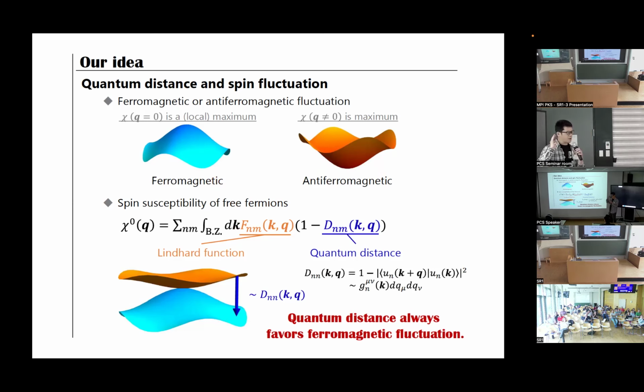So let me discuss the curvature of spin magnetic susceptibility. Here I am showing the formula of spin susceptibility of free fermions in multiband systems. Here we see the quantum distance. By this formula, we immediately notice that the quantum distance always favors the ferromagnetic fluctuation rather than the anti-ferromagnetic fluctuation. This is because the quantum distance must be positive, and it disappears at Q equals 0. This means that the quantum distance suppresses the anti-ferromagnetic fluctuation, leading to dominant ferromagnetic fluctuations.